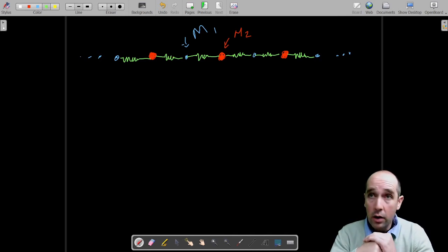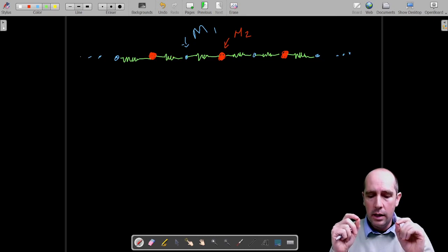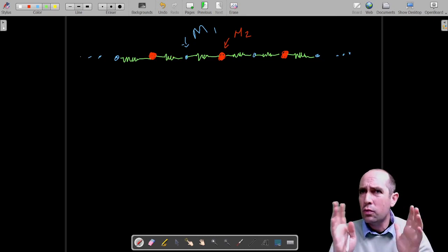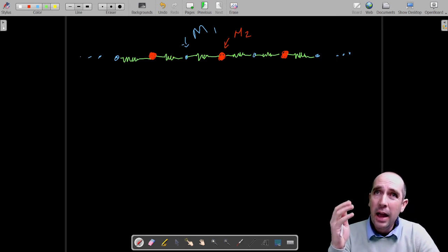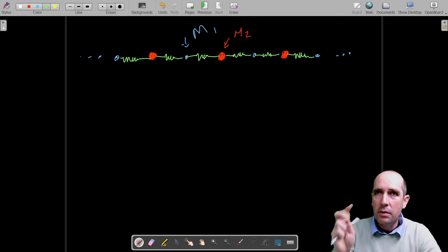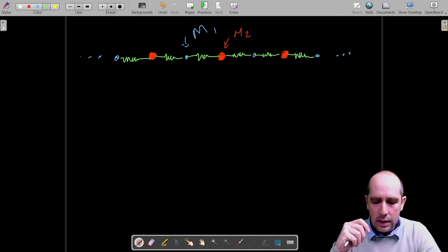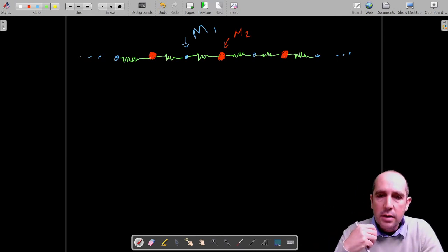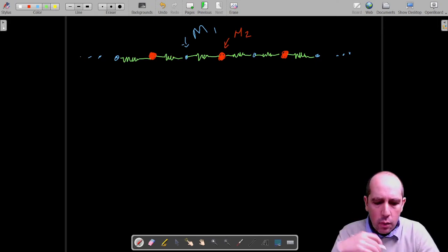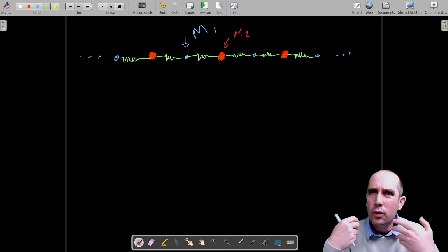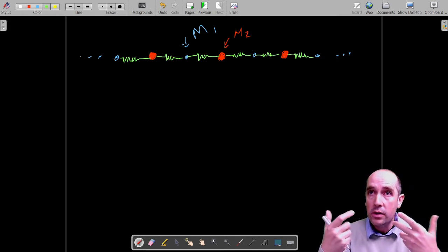But as long as the perturbation is small, and if there is an equilibrium position, which we know there is, the essence behind this idea is correct, because any potential with a minimum can be approximated within a certain range as a harmonic oscillator, and we all know that as a parabolic potential. So essentially, using this harmonic approximation, what we can do is we can try now to write down the motion equations for these two types of atoms.